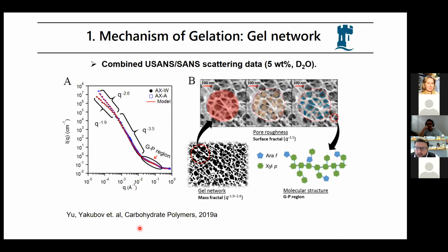And of course, we can't trust microscopy, so we need to go to scattering. Here we used an opportunity of doing ultra small angle neutron scattering and small angle neutron scattering, and we could see that the difference between the two is very small, and it's all at the very low Q. That's a higher level of the network arrangement. So at the nanometer and 100 nanometer scale, these gels are totally identical. It's just the higher level structure that is slightly different between the two.